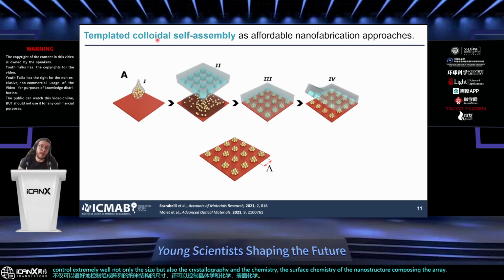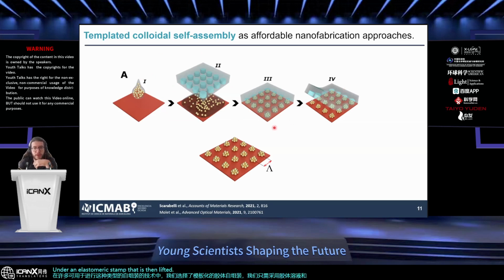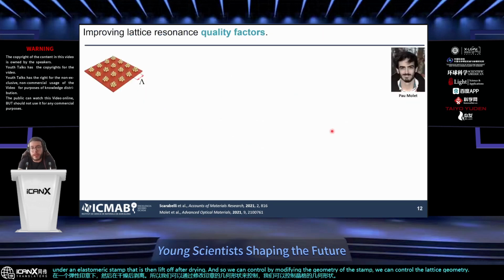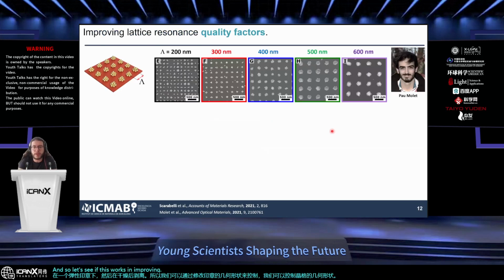And so amongst many techniques available for this type of self-assembly, we picked templated colloidal self-assembly, where we simply take a colloidal solution and let it dry under an elastomeric stamp that is then lifted off after drying. By modifying the geometry of the stamp, we can control the lattice geometry. Let's see if this works in improving the quality factor. Here we have a few SEM pictures of the types of arrays that we can produce in the lab using 50 nanometer nanoparticles.